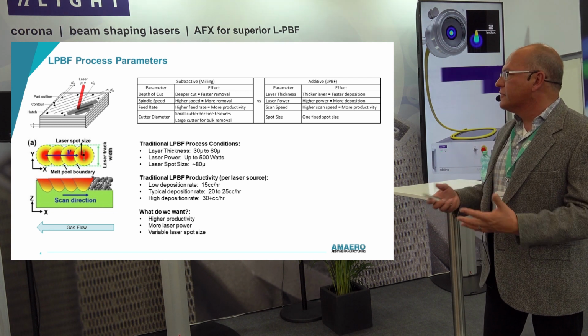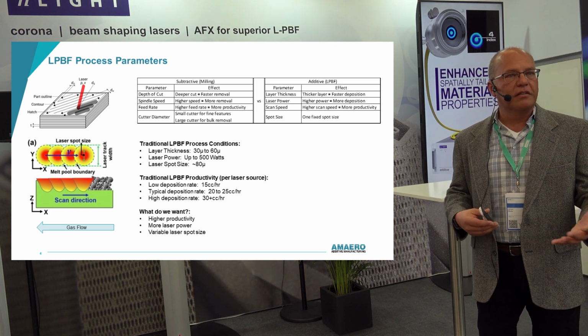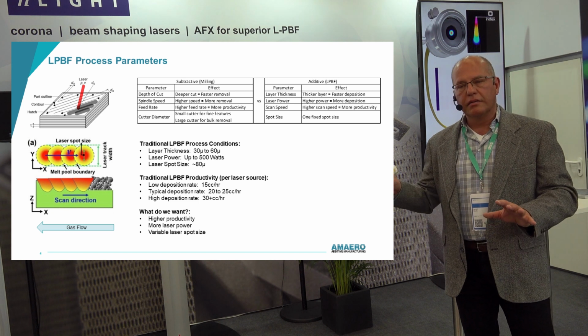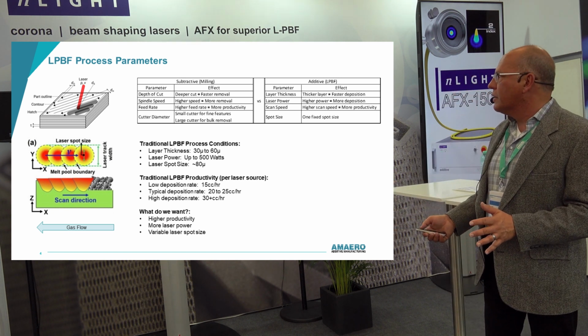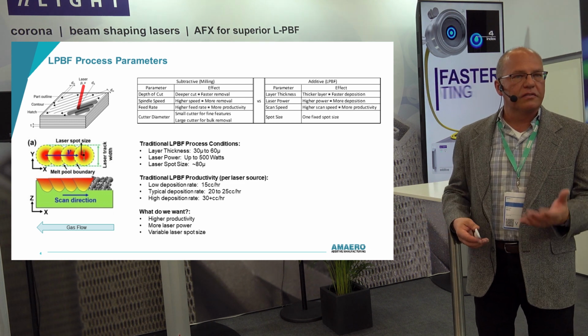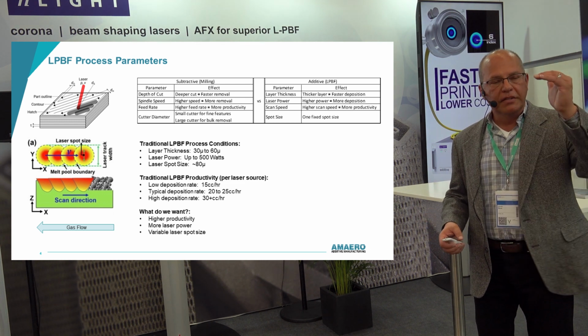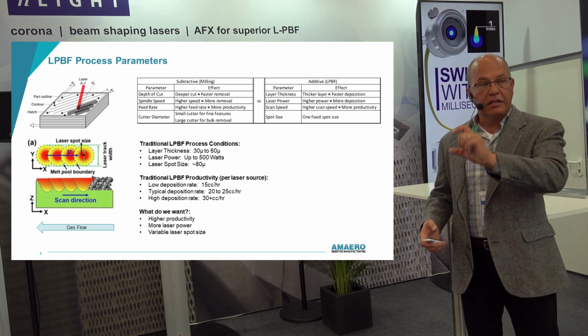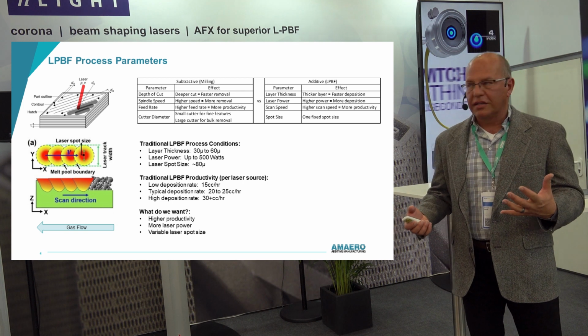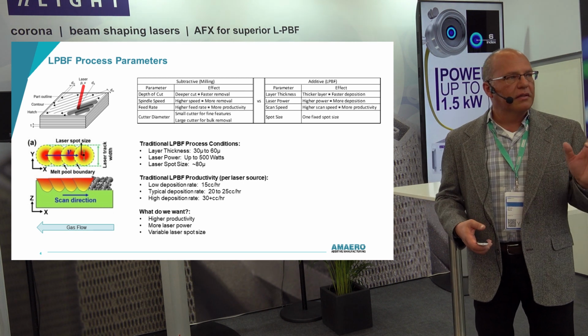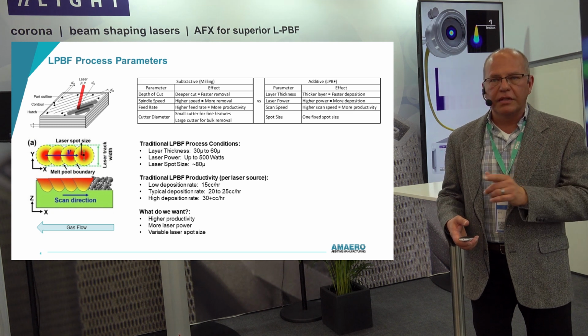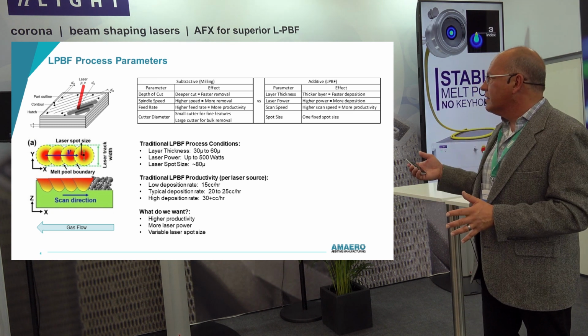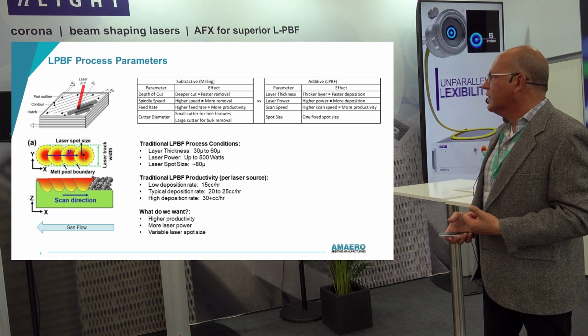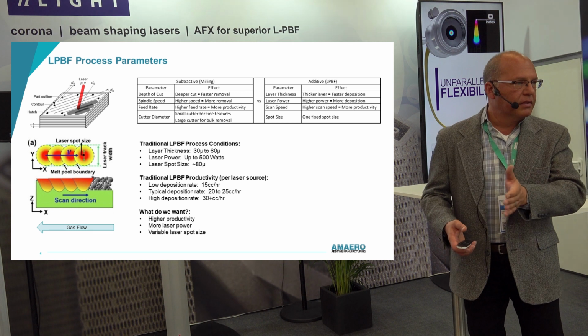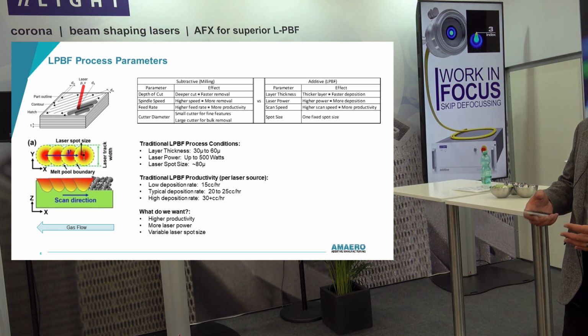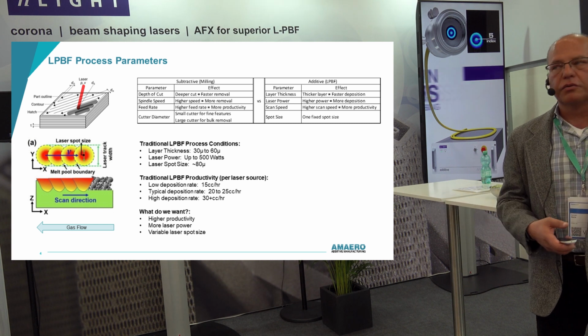But in terms of how this all works, we can also think about it compared to subtractive manufacturing. We talk about feeds and speeds. In printing, we call it parameters. So the depth of cut in milling is just like our layer thickness in printing. The deeper the cut, the more material we can take away. The thicker the layers we can print, the more material we can deposit. Our spindle speed addresses how much material we can remove in a given time, and the laser power lets us deposit more material. Our feed rate, moving the part past the mill, increases productivity, and our scan speed, if we can scan faster, increases productivity.